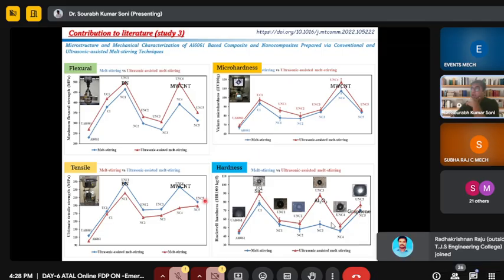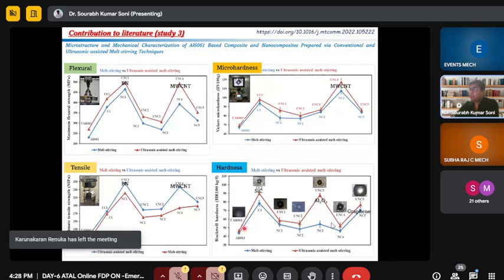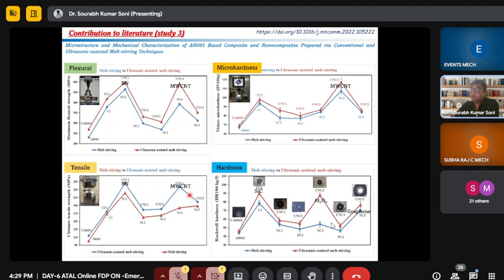Reviewers are always asking. So we can relate that SiC, Al2O3 and graphene are ceramic particles. These ceramic particles are responsible for improvement of the hardness, and the MWCNT tubular structure is responsible for improving the mechanical property, or BN nanoparticles are very promising to improve the mechanical strength of the resulting composite. So you can relate your nanoparticle with the resulting properties.